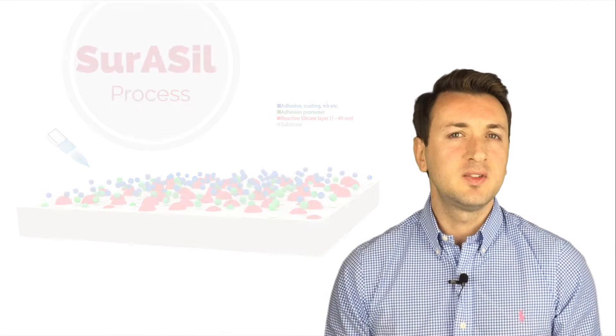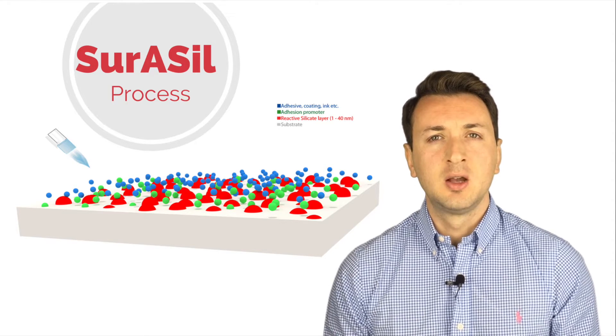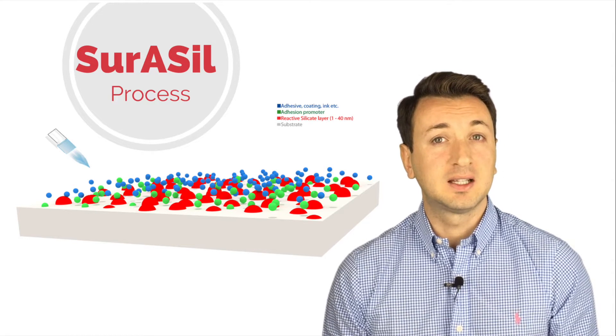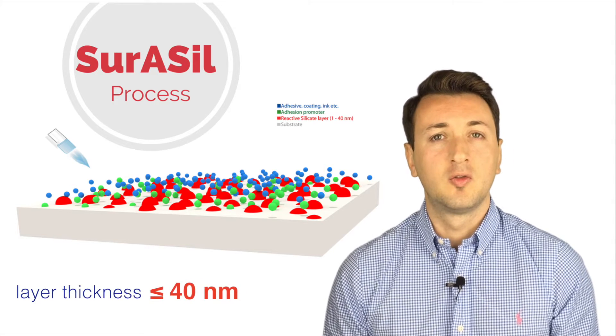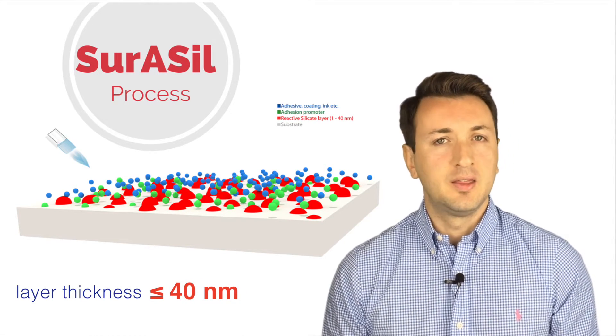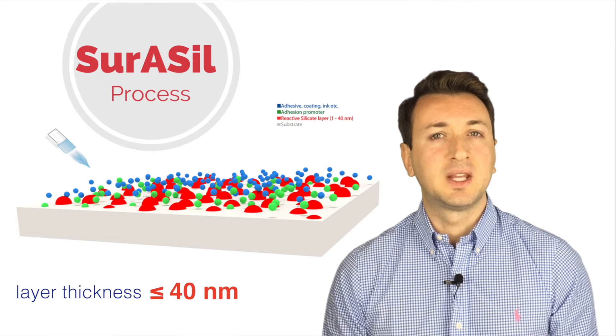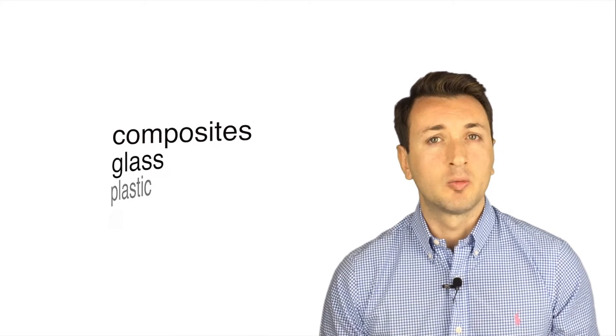The CCVD coating process is used to drastically improve the adhesion of surfaces by depositing a very thin adhering silicate coating with a maximum thickness of only 40 nanometers, yet very dense. In this way the substrate material obtains a highly adhesive surface. The material can be metal, ceramic, plastic, glass, or a composite.